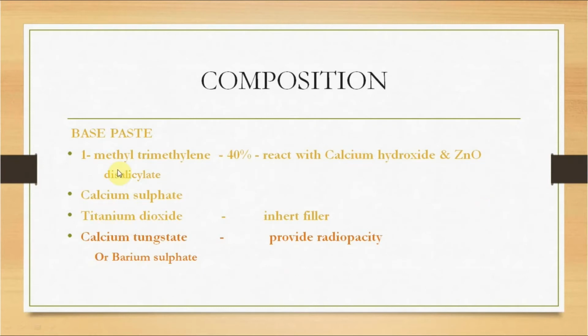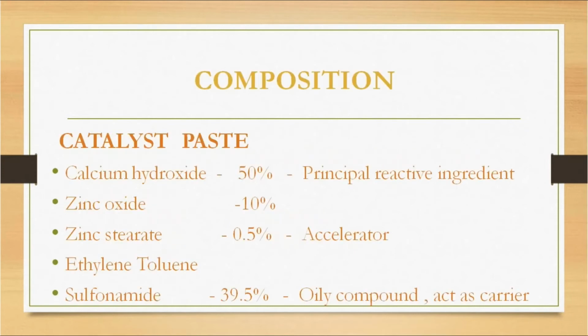Composition. Base paste contains 1-methyl trimethylene disalicylate 40%, which reacts with calcium hydroxide, and zinc oxide, calcium sulfate, titanium dioxide as filler, calcium tungstate or barium sulfate which impart radio opacity.